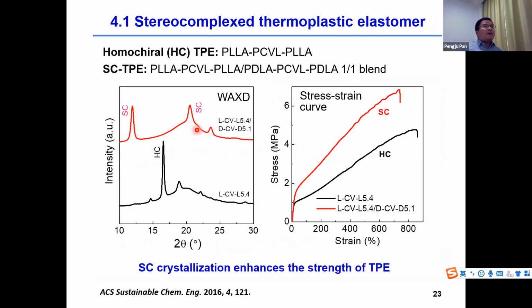From the WAXD pattern, we can see the homochiral copolymer forms the PLA homocrystal. The L and D mixed copolymer forms stereocomplex crystal. With the crystallinity of these two elastomers, the stereocomplex elastomer has a higher strength and modulus than the homocrystalline one. This shows the stereocomplex crystallization can reinforce the thermoplastic elastomer.